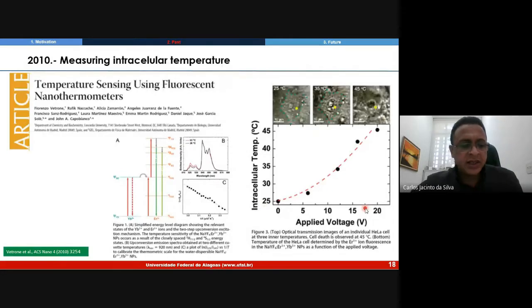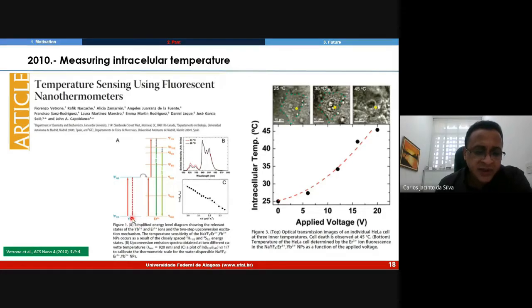At the cell level, an important temperature sensor is based on nanomaterials because it is possible to obtain local or intracellular temperature. The first detection of intracellular temperature used an optical nanothermometer based on lanthanide ions, in this case erbium-ytterbium codoped nanocrystals, using the two thermally coupled levels emitting in the green. It should be noted that these luminescent nanothermometers operate in the visible region, but even so it's possible to obtain intracellular temperature. The green is not ideal because it's outside of the biological windows, and suffers very strong absorption by the tissue.